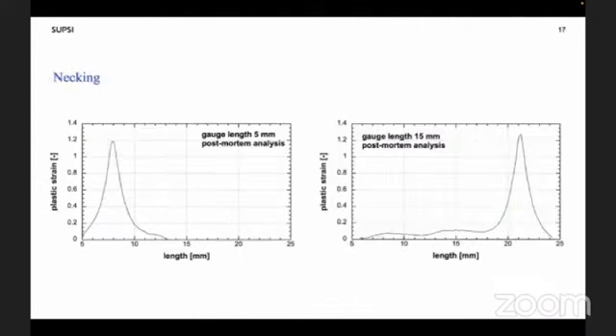On the basis of this measurement, the plastic strain is derived from the natural logarithm of the ratio between initial and final cross-section. Two observations can be done. First, the dimension of the necking zone is constant, as well as the failure plastic strain. The second observation is that in the longer sample, the plastic strain shows variations that indicate possible plastic localization in the pre-necking phase.